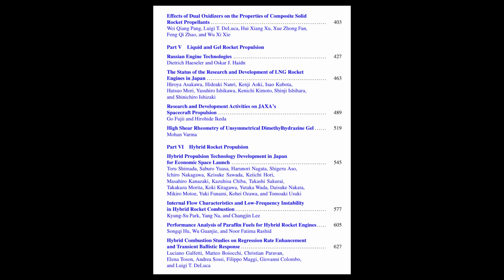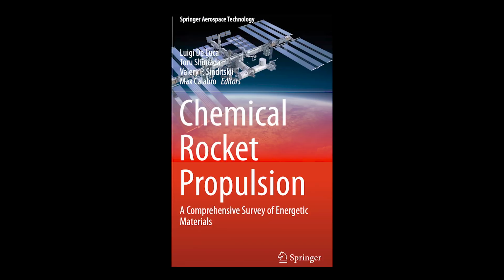Like rust on iron. Sort of, but it's an aluminum oxide layer. And for really small particles, say under 20 nanometers, that oxide shell can actually make up a significant chunk of the particle's total mass. And that's bad because... Because the oxide doesn't release nearly as much energy as pure aluminum when it burns. Plus, that shell increases the temperature needed to even get the particle to ignite. It reduces energy and makes it harder to light.